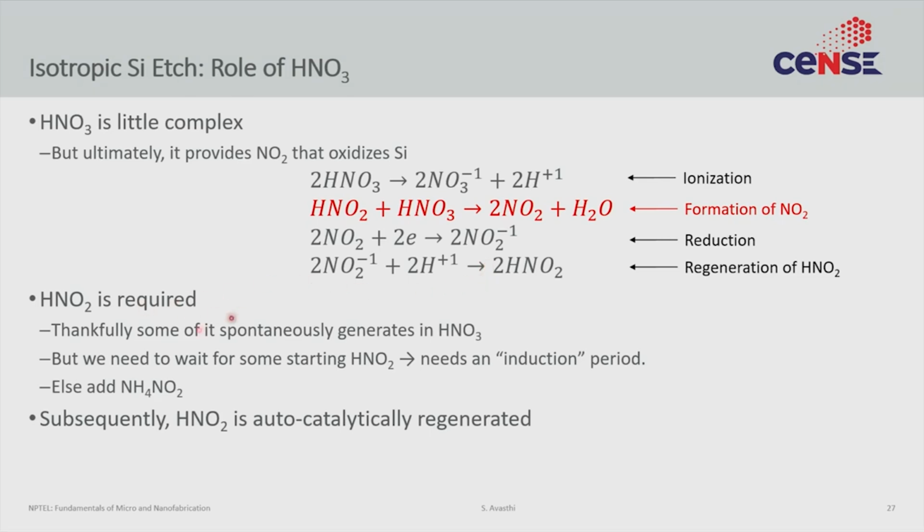Okay. So HNO2 is thankfully spontaneously generated. We don't have to worry about it. It's not something we have to explicitly add. However, this does create an interesting issue that sometimes the HNO3 solution is not active from the get-go.